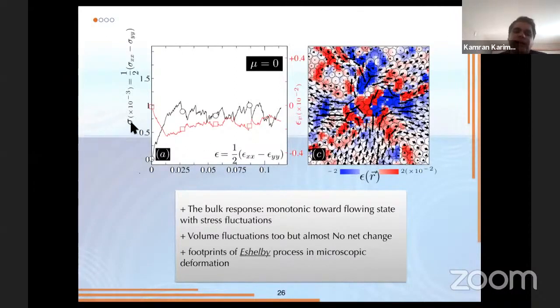If you look back at the response, there is an initial quasi-elastic regime, which corresponds to initial compression, and then the system enters a plastic flow regime with these bursts, which is also apparent in the volumetric strain, which fluctuates, but there is almost no net volume change. So the system flows like an incompressible solid.